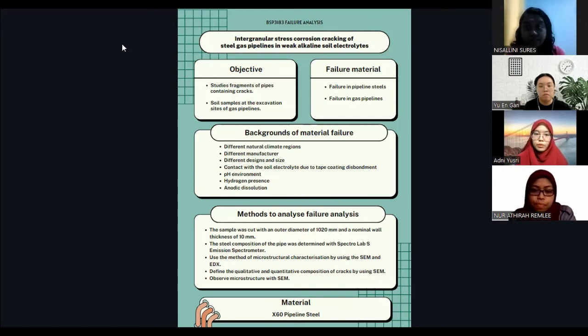So we move to failure material. The first failure material is failure in pipeline steel, and the second is failure in gas pipeline. For failure in pipeline steel, local anodic dissolution of the metal has a major effect on crack growth in pipeline steel in weakly acidic and neutralized electrolyte. And then the failures in the gas pipeline are related to stress corrosion cracking with signs of the intergranular character of propagation into the depth of the metal, according to the mechanism of local anodic dissolution of the metal at the grain boundary.